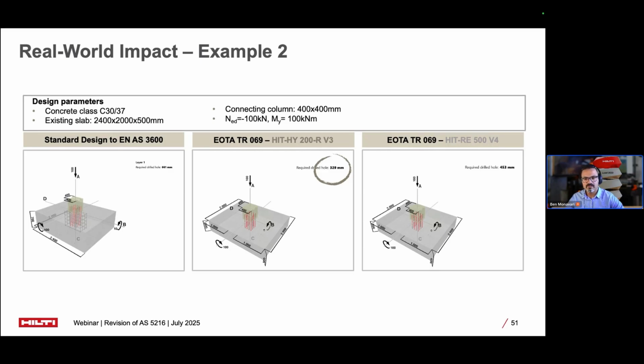So in your design, I suggest to check which one gives you a better capacity, if it's possible to use HY200, because it's a fast cure epoxy. So for long depth, especially for rebar applications, I would suggest to go with RE500V4 because it's a slow cure epoxy and it gives you more time to inject the chemical and install the rebar. So this is a 50% reduction. This represents substantial cost saving, reduced drilling time, improved construction safety, and enhanced sustainability through reduced material usage and construction impact. So it's not just about saving on the epoxy, also the construction, the installation, and everything is going to be saved as well.